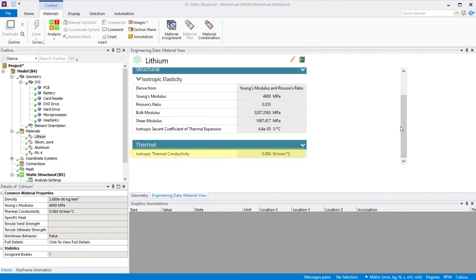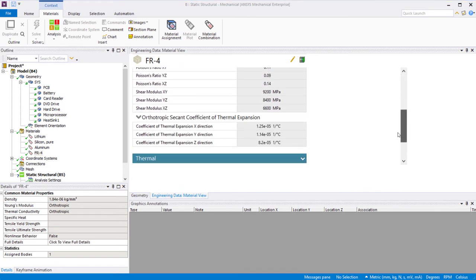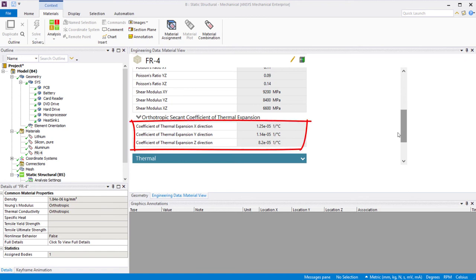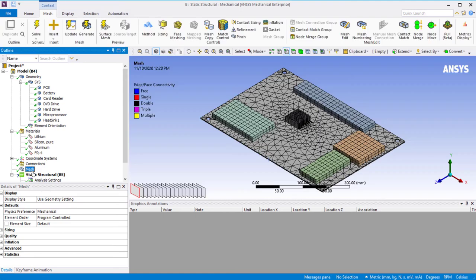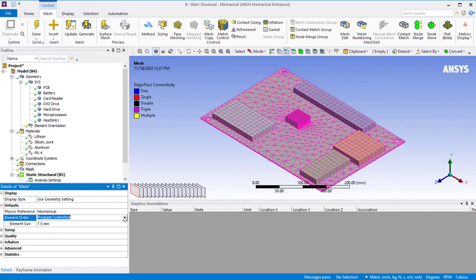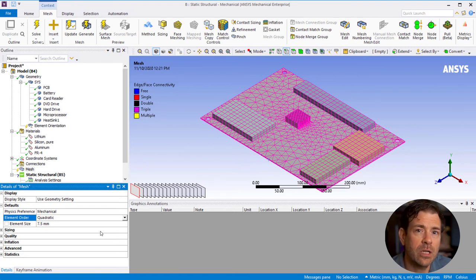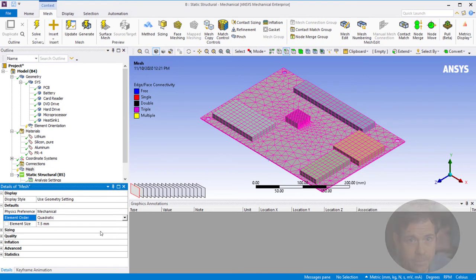But in order to perform a thermal stress analysis, in addition to the usual elasticity moduli and Poisson's ratios, we also need to define the coefficient of thermal expansion, or CTE in short, for each material. For a material like FR4, which is orthotropic, just like we define different elasticity moduli and Poisson's ratio in different directions, we may need to define different CTEs for each direction. Next, let's define the mesh. Let's set a similar element size to what we had in the thermal analysis. But instead of using linear elements, let's set the element order to be quadratic. We do this to avoid using linear elements, which are inherently stiff, and especially because we have a thin part with only one element in the thickness direction, where the linear tetrahedron would not accurately capture the bending response. Now generate the mesh.